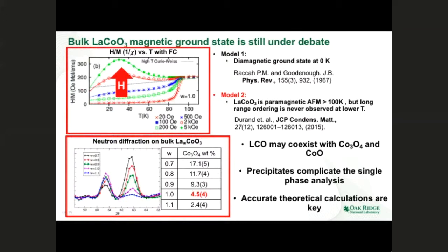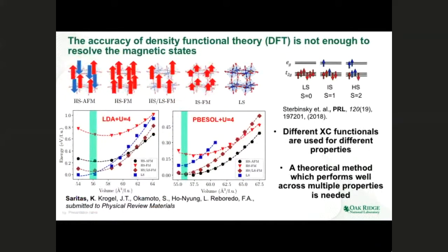So it is also known that this material would prevent experimentalists from getting a clean measurement of the magnetic properties of these samples near 0 Kelvin. With this motivation, we set out to calculate lanthanum cobaltite using diffusion Monte Carlo. We looked at 5 different magnetic structures of the bulk structure. We know that cobalt is in the +3 charge state, so it should have 6 valence electrons. Based on that, we can have 3 different magnetic states on each cobalt atom: low spin, intermediate spin, and high spin.